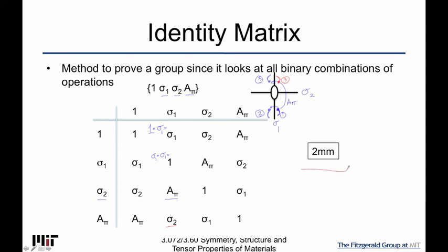So by inspection, we've already derived our first point group. That's not a new thing, right? I mean, remember we had developed all of the rotations ahead of time, right? Because we put them in the lattice. We saw that these are rotations that are compatible with translational symmetry. And so we're not going to do any ones outside it, like fivefold axis, because they aren't compatible. You could have a point group, by the way, with 5, because it's not in a lattice, right? But we're not going to play around with that, because what we care about are the symmetry elements, which can be put into a lattice.